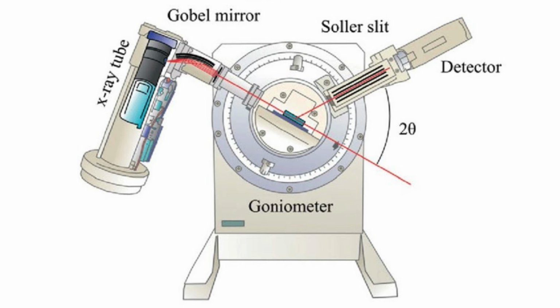Modern XRD systems typically operate using a theta-2theta geometry in reflection mode. In this arrangement, the sample rotates by an angle θ, while the detector moves simultaneously at an angle 2θ relative to the incident beam. This synchronized motion ensures accurate measurement of diffracted intensities and enables precise determination of interplanar spacing.